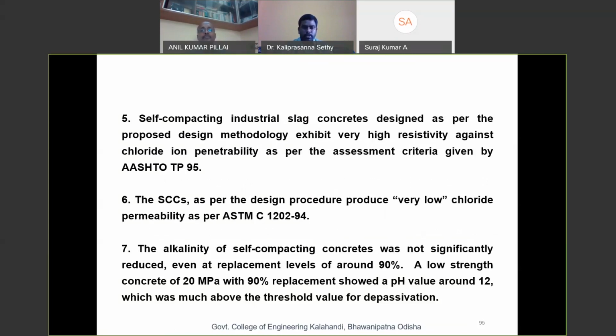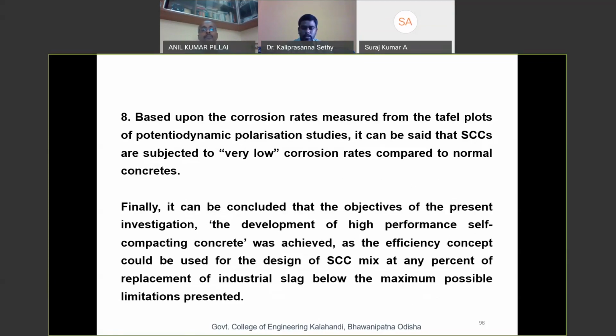The alkalinity, that is the pH value of self-compacting concrete, was not significantly reduced, even at replacement levels of around 90%. A low strength concrete of 20 MPa with 90% replacement showed a very good pH value around 12, which was much above the threshold value for depassivation. And based upon the corrosion rates measured from the Tafel plots of potentiodynamic polarization studies, it can be said that self-compacting concretes are subjected to very low corrosion rates compared to normal concretes.